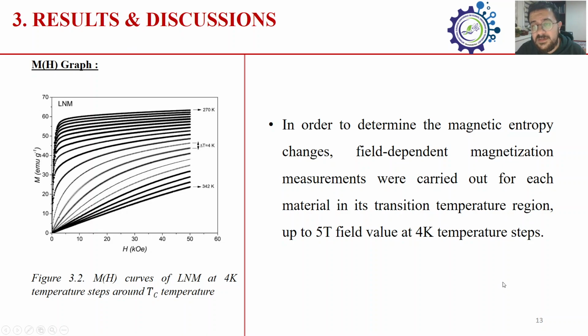In order to determine the magnetic entropy change, field-dependent magnetization measurements were carried out for each material in its transition temperature region up to a 5 Tesla field value at 4 Kelvin temperature steps. In this MH graph, if you look at the magnetization curves, they dramatically increase in the low temperature region and linearly increase at higher temperature, and this is the result of the fast transition from ferromagnetism to paramagnetism.